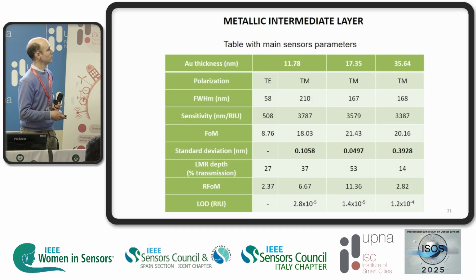So in this table, we summarize the parameters. There is not a great improvement in terms of figure of merit with 12 nanometers, 17 and 35. We get 18, 21, 20. It is better with a thickness of around 20 nanometer, but the improvement is not very high. But the standard deviation is improved by a factor of 2 compared with this sensor, and by a factor of nearly 10 with the other one. So the important thing here is that with a metallic intermediate layer we can tune the depth of the LMR.